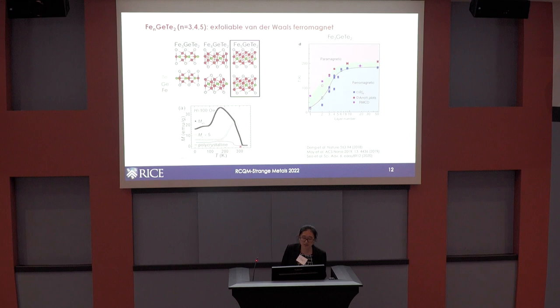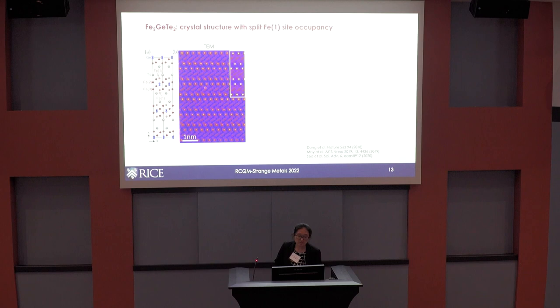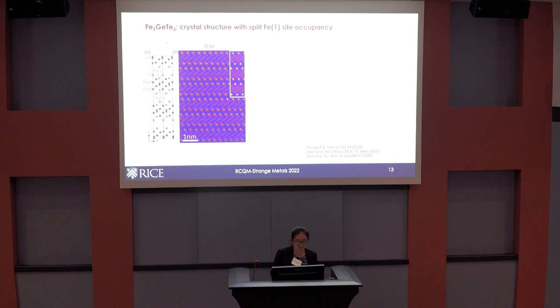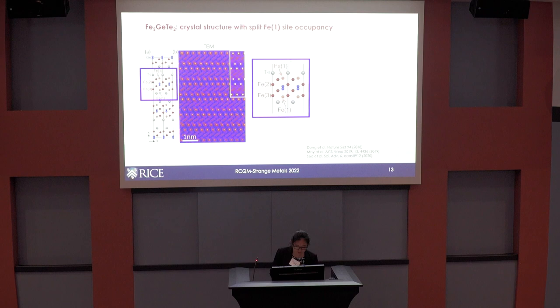There's something very special about the 5-1-2 material: an additional degree of freedom not present in 3-1-2 and 4-1-2. A single unit cell of FGT 5-1-2 consists of three ABC-stacked Van der Waals layers. Within a single slab, the outside atoms are tellurium, the blue atoms are germanium, and the rest is iron. Among all the iron sites, there are three distinct iron sites. This is very important — the inversion center of the single slab is right between the two blue germanium sites.